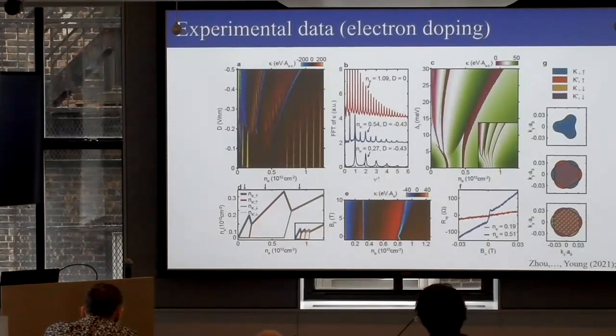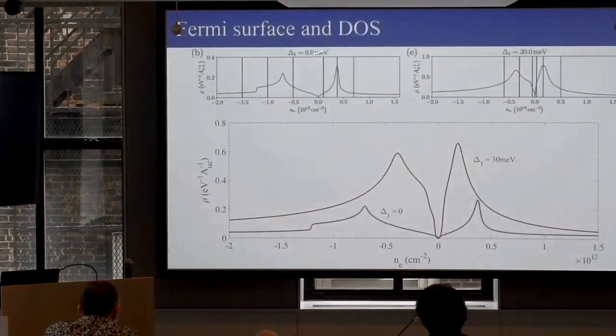So this is the experimental data. I'm not going to go through the experimental data because I don't remember all the details. You have to trust Andrea that he did things right, and he found fragile superconductivity, on the order of a Kelvin, at very specific points. So this is the dense Fermi surface. This is the calculated band structure, Fermi surface, the density of states of tri-layer graphene. Okay, so you can see the Van Hove singularities, but superconductivity happens near it, but not exactly at it. And this was always Pablo's point, that if it's the kind of electron-phonon mechanism we are talking about, superconductivity should be just around this.